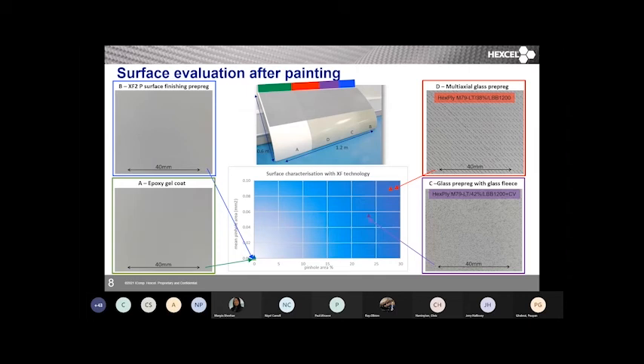And we built the four technologies side by side. You can see that section A is white, so that's the opaque gel coat that would traditionally be used. And then the grey bar at the top, that's where we've applied a standard paint to the panel. If we whiz round clock fashion from top right, from the red box, that's what you would get in terms of surface finish if you applied a multi-axial fabric straight onto a composite mold and tried to make a wind blade. And the graph at the bottom is trying to show you that that's a bad starting point, which is no surprise.